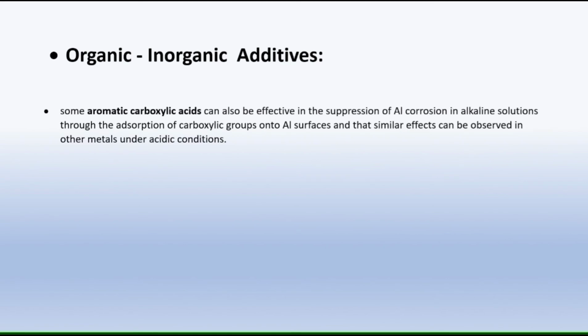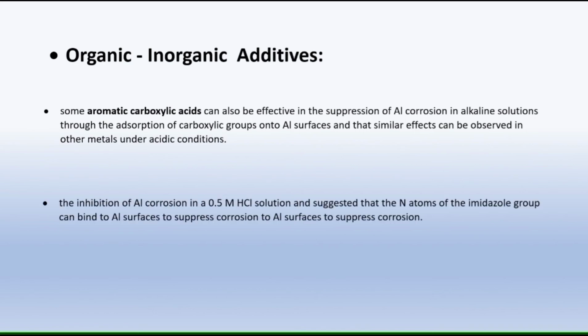Organic and inorganic additives. Some aromatic carboxylic acids can also be effective in the suppression of aluminum corrosion in alkaline solution through the adsorption of carboxylic groups onto aluminum surfaces, and similar effects can be observed in other metals under acidic conditions. Researchers studied the inhibition of aluminum corrosion in 0.5 molar HCl solution and suggested that the N atoms of the imidazole group can bind to the surface of aluminum to suppress corrosion.